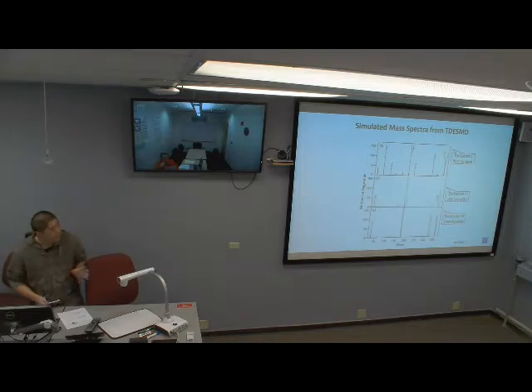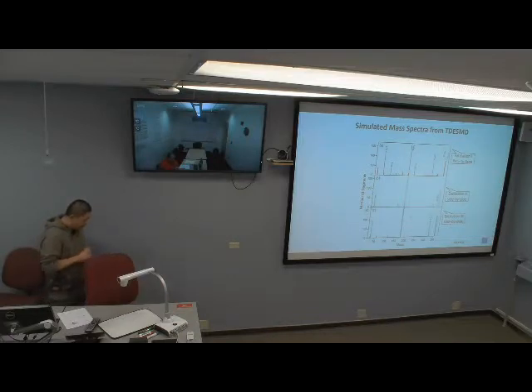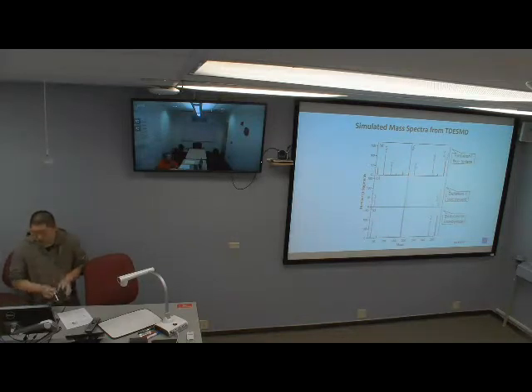Okay, so finally we can build a simulated mass spectrum. The dominant peak is the monomer, Si6H12. For the first spectrum, we also observe the dimer peak, Si12H24. But this dimer peak is missing for spectra B and C. This is because for the simulation starting with face-to-face configuration, dimerization happens before dehydrogenation. But for simulation starting with side-by-side configuration, dehydrogenation happens before dimerization.